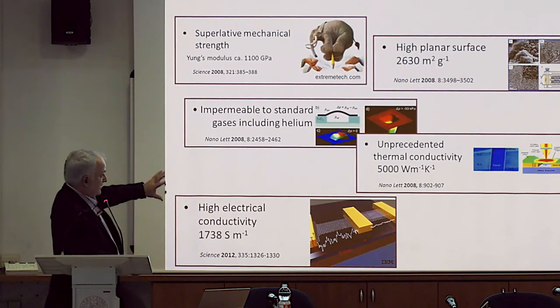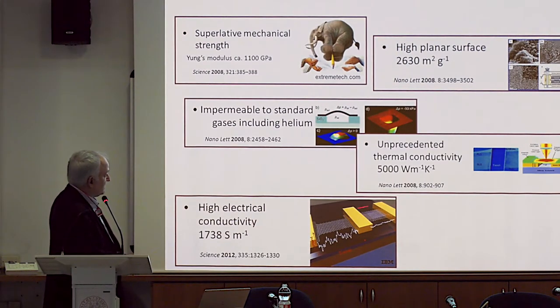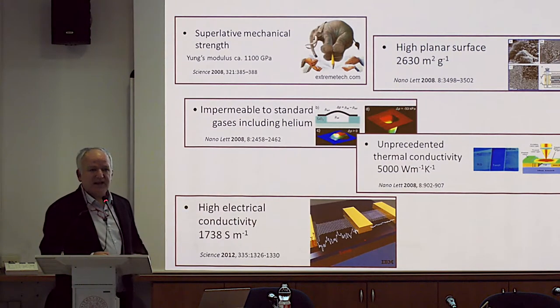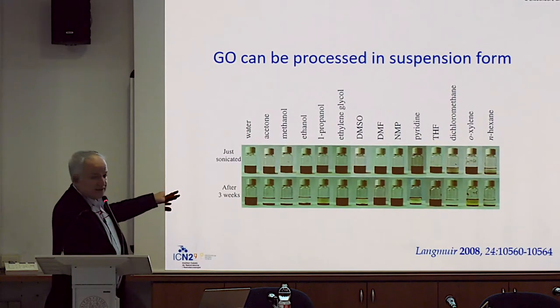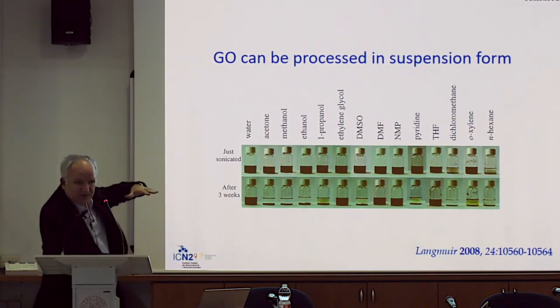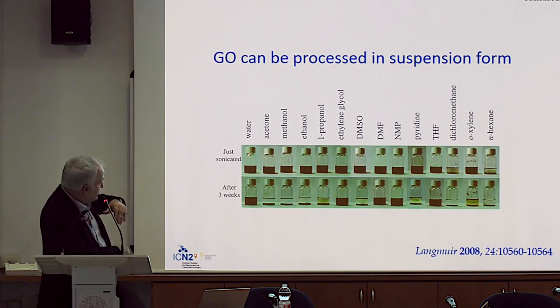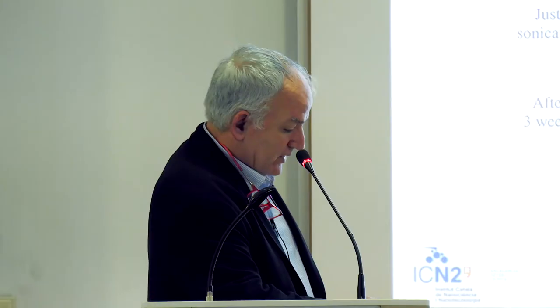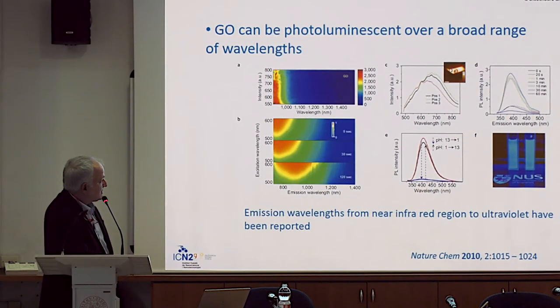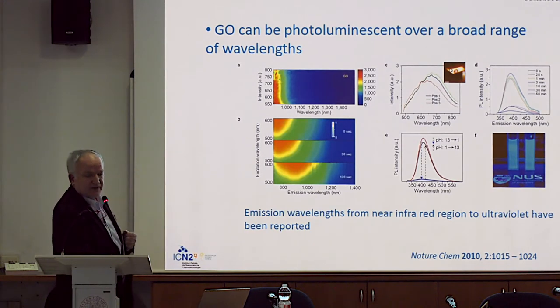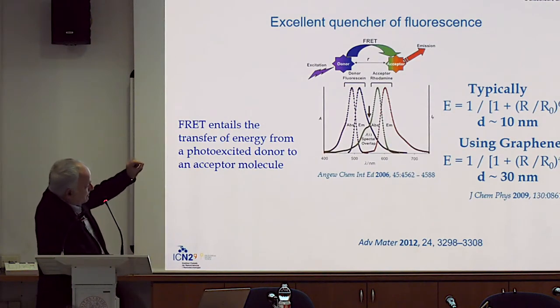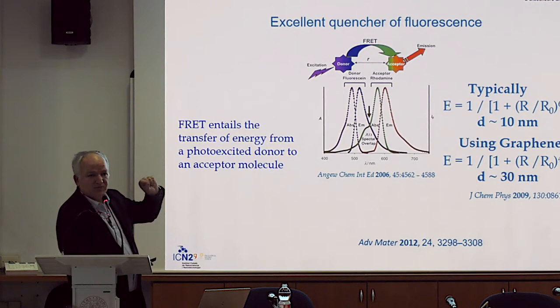And in fact, there are nice properties, mechanical properties, strength, but also very nice optical and electrical properties. This material also can be processed in solution, so we can have these flakes of graphene in solution, interestingly in water also. And you see here, it is also very stable, which is very interesting for biosensors. We can connect any kind of receptor to this material, and as I said, optical properties are really very interesting. So this material is photoluminescent over a broad range of wavelength, and we use this property to apply this in biosensors. So one interesting property is the quenching of the fluorescence that is induced by graphene oxide.